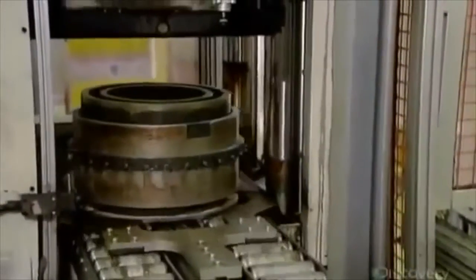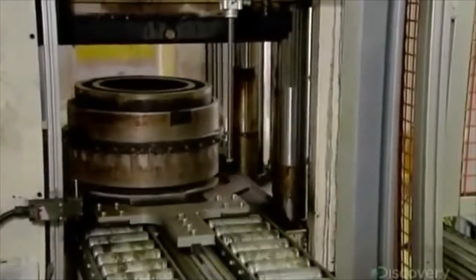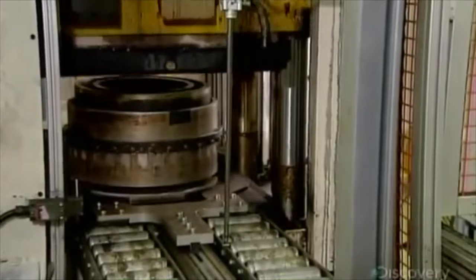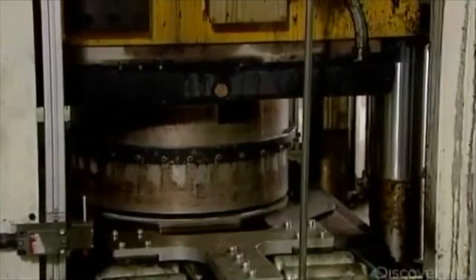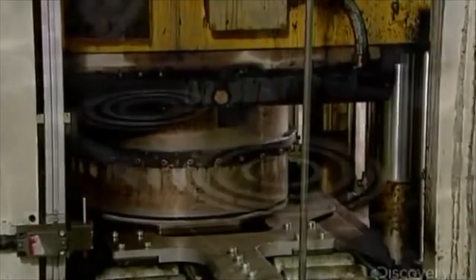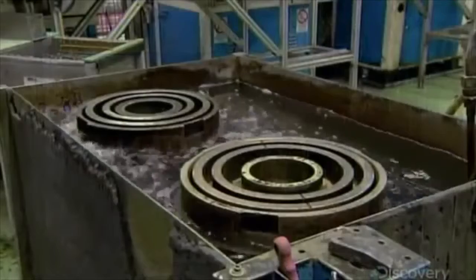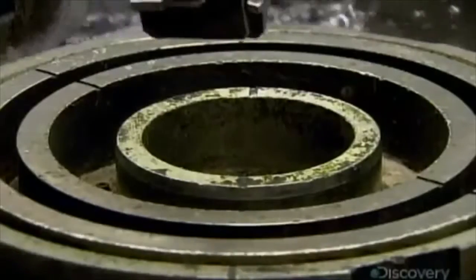20 tons of pressure is applied to the mold as it is heated to 400 degrees Fahrenheit. This intense pressure and heat compacts the carbon fiber and melts the resin into plastic. After this process, the mold and part are then water cooled for 5 to 8 minutes.